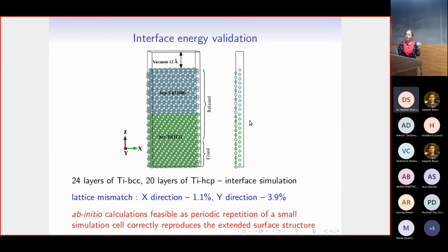What you're seeing here is 24 layers of the titanium BCC interfaced with 20 layers of the titanium HCP. In this case, the lattice mismatch along the x direction is 1.1%, along the y direction is 3.9%. Although the lattice mismatch is large, what we saw is that whatever the number of repetitions we do in the x and the y direction, this lattice mismatch stays the same.